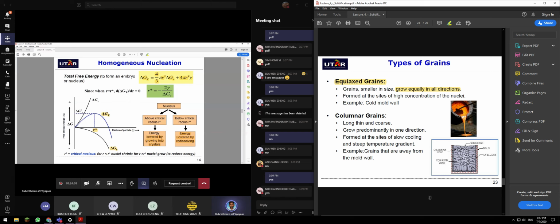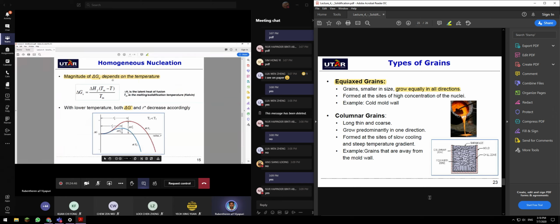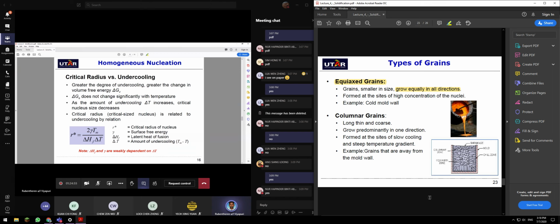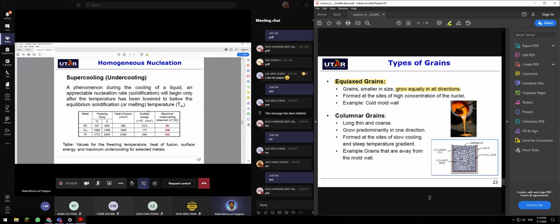Here, in order for the transformation to take place, GT must follow GV, where the magnitude of GV must be higher than the magnitude of GS. So GT is the sum of GV and GS, and this is your critical radius. Atoms below the critical radius are predominantly dominated by GS, so they will never reach nucleation. Atoms above the critical radius, predominantly dominated by GV, will eventually turn into crystals and grains. The magnitude of GV depends on temperature. This is the formula. Critical radius and undercooling, this is just side information for you, and supercooling as well.